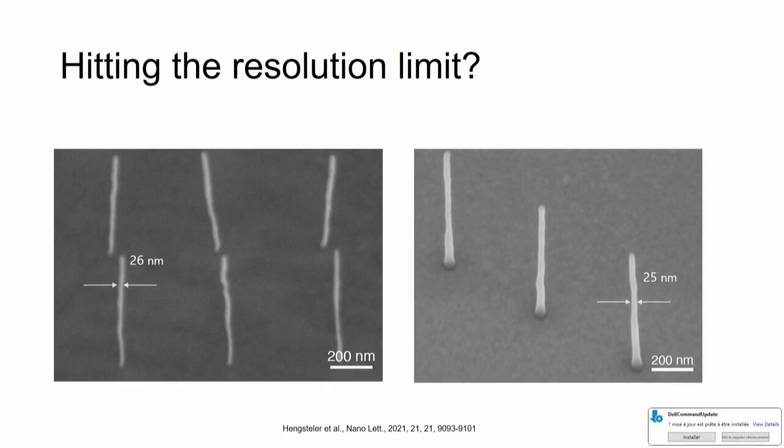And then when we started to use these nozzles, we found out that actually the structures that we print are not suddenly that small. When it's reproducible, we were always limited at around this 25, 26 nanometer mark. And if it is irreproducible, you can go to the scale around 10 nanometers, but it doesn't really work reliably. Anyway, I will skip the reason why this is happening.